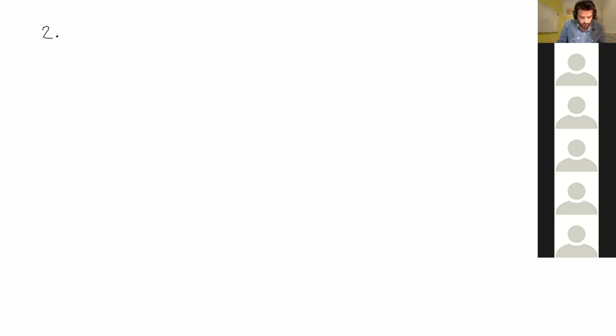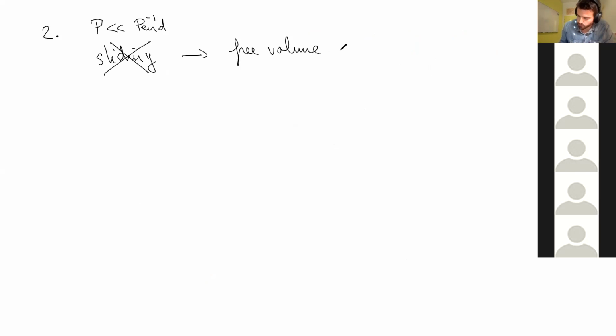But you see, the mechanism by de Gennes doesn't work at all in the bulk, because in the bulk, you first need a standard glass relaxation from the first monomer, and then behind you have an additional price. Even though this price is small, you have to pay it. And there is a huge number of objects, so N here is very large. So it's unlikely that in the bulk, the sliding mechanism will be efficient. But everything will be different if we go to interfaces. So sliding inefficient, and we keep to the free volume picture in the bulk.